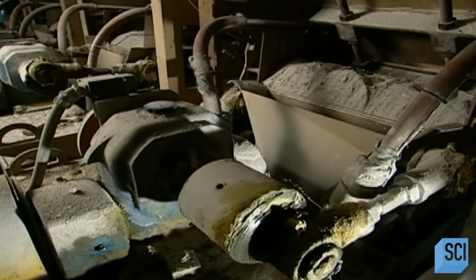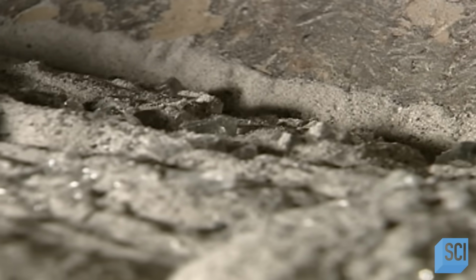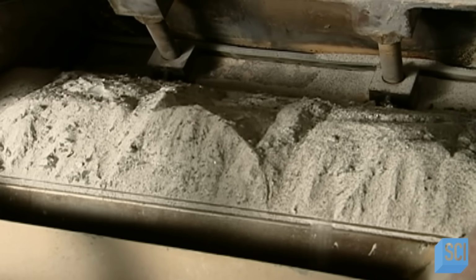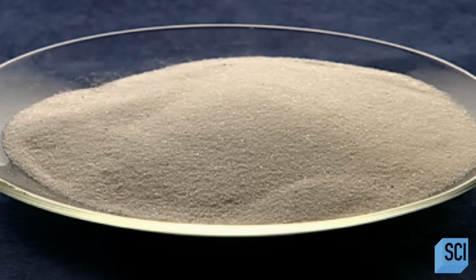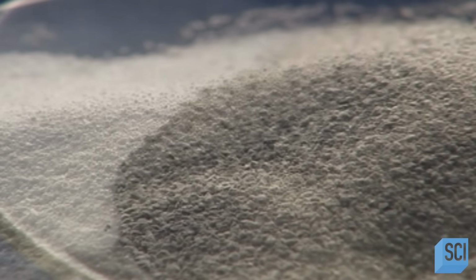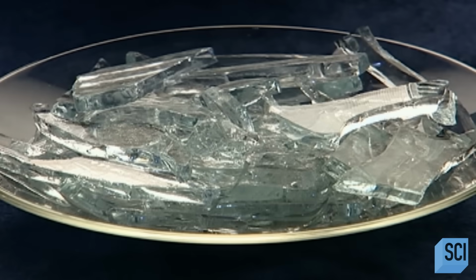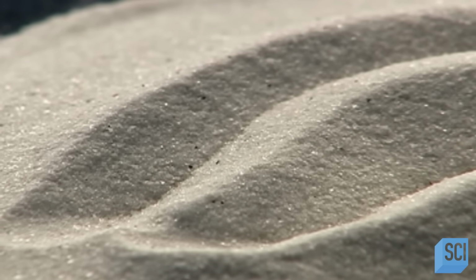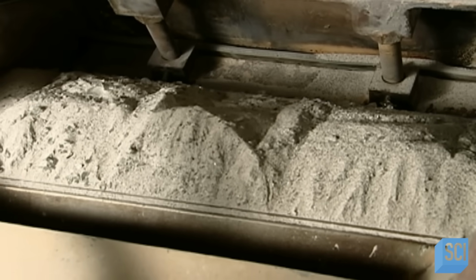To produce some dishes, a batch feeder pushes ingredients into a big furnace as they spill out of a bin overhead. Silica sand is the biggest part of the mix. It's a crystalline substance and it makes glass transparent. The batch also includes soda ash and recycled glass. Some of the other ingredients are a trade secret. The furnace heats the mix to the melting point, over 2,700 degrees Fahrenheit. It turns into molten glass that looks like lava. The glass in this lava-like form will spend up to 24 hours in the furnace.